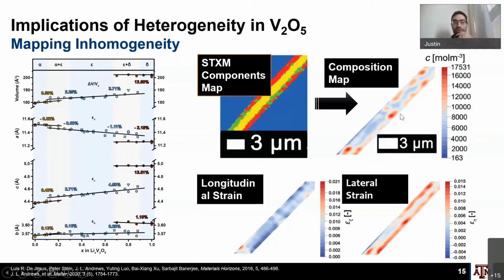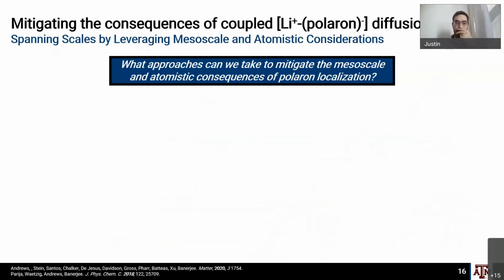And then from there, through some phase field modeling, we can actually get at what the actual local strains are at the boundaries between these different phases. And in terms of brittle oxide materials, these strains can be very, very high. So this is an issue.